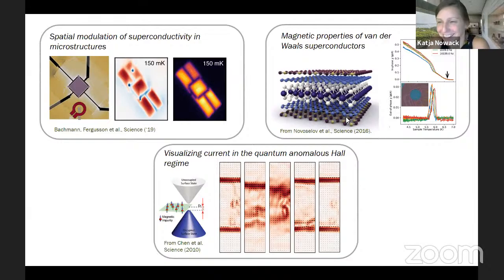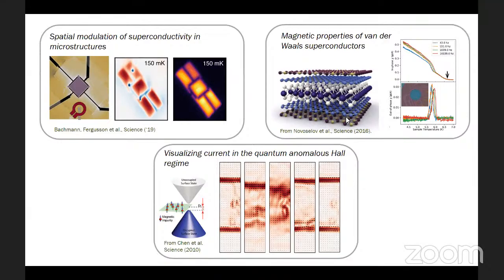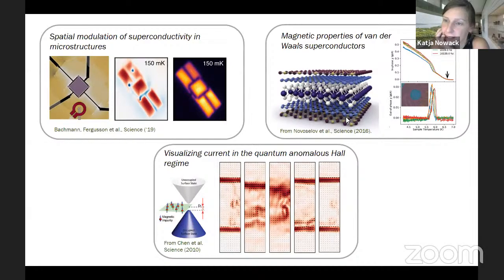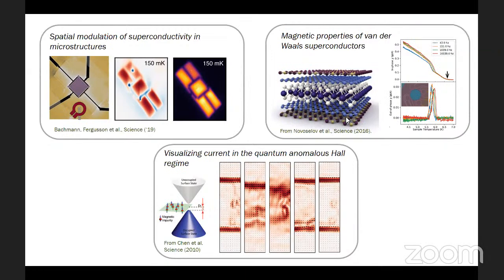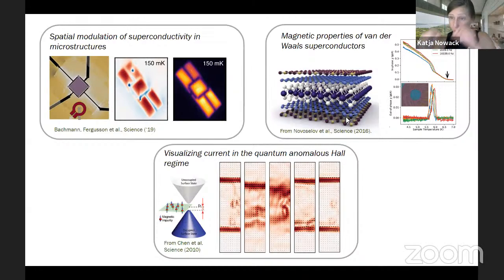It's complicated. I wish I had a good way to quantify that. But you're right, it is a function of both. One experiment that we at some point want to do is image arrays of, say, superconducting stripes, and vary both the thickness and the distance between those stripes, which would allow us to put some hard numbers on what we think the spatial resolution really is. But even if we had that number, it doesn't really answer the question of what the spatial resolution is if we image a completely unknown non-uniform superconductor. So I'm dancing around the answer.